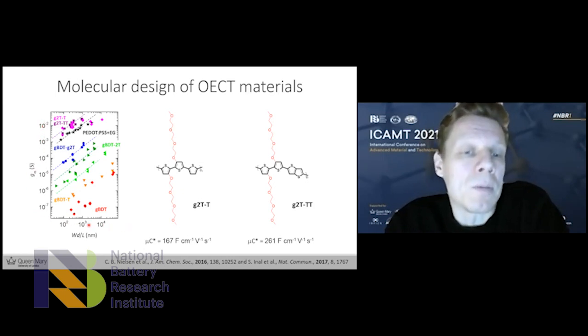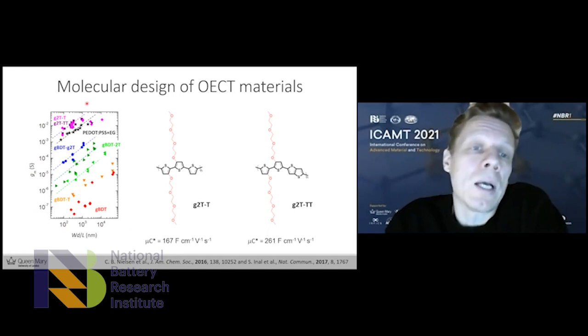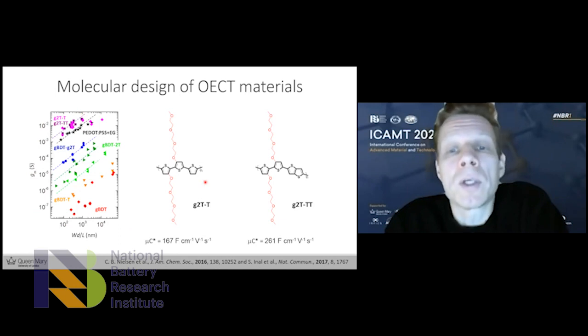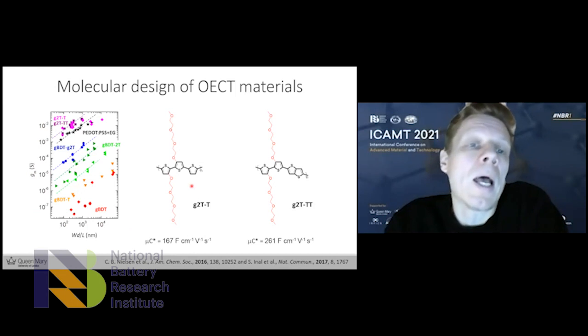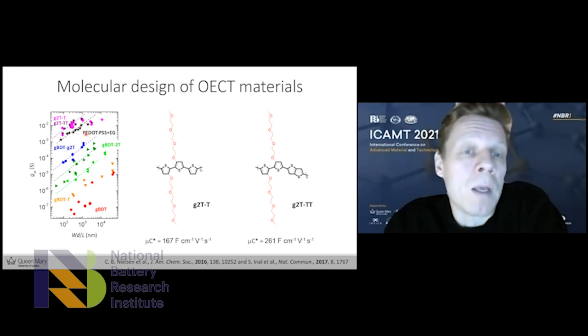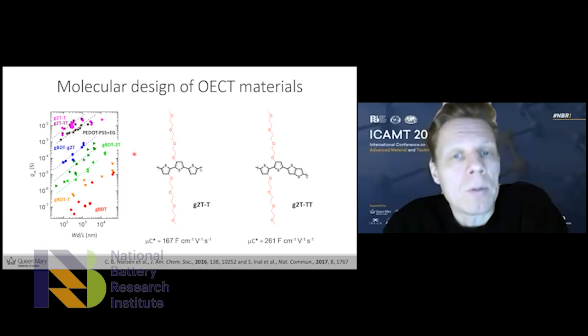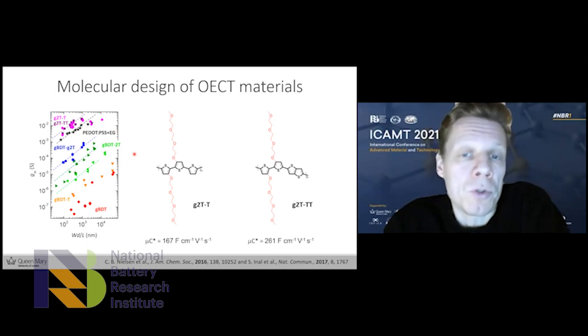And on the x-axis, we have the dimensions of the active layer, which I also mentioned plays a role. So when we compare materials, we need to compare them across the same dimensions of the active material. But you can see here at the top, at high transconductance values, we have these new materials, these polythiophenes with polar side chains that we developed, and they perform very, very well. The black stars data points here are from one of the conventional PEDOT materials that people used as the benchmark material for mixed conduction. And you can see our new materials here outperform the benchmark PEDOT:PSS material in all dimensions, more or less. So this materials design rule about adding these ethylene glycol chains onto the material is sort of emerging as a universal way of introducing mixed conduction in these materials.